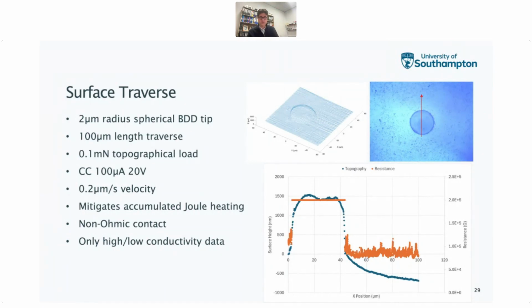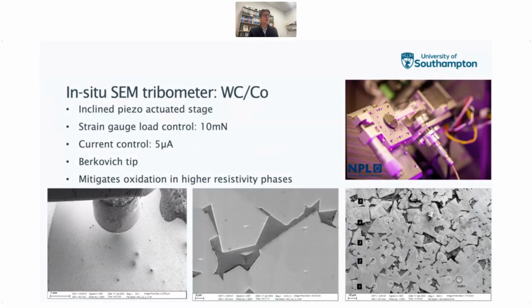We're not really getting anything more useful than that out of it. The other thing we tried is to then move it to an inert atmosphere or vacuum atmosphere. We went to the National Physical Laboratory there to use their in situ scanning electron microscope tribometer, which you can see has this inclined piezo actuated stage with the strain gauge load control on the indenter tip. And so we could then put our Berkovich tip into these different phases.